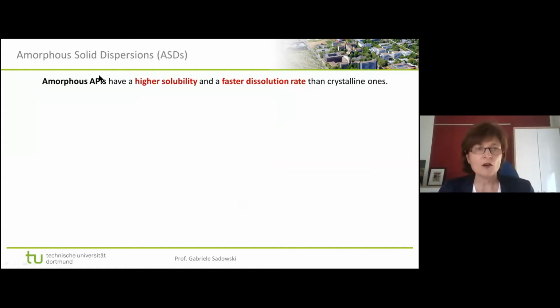So what is known is that an amorphous API, compared to a crystalline one, has a higher solubility than the crystalline one, and just as important, a faster dissolution rate. You not only need something that dissolves in water: if you take a tablet, you have about 1 or 2 days for the tablet going through the body, and only what's dissolved during this time is what you can really have in the body to do the job.